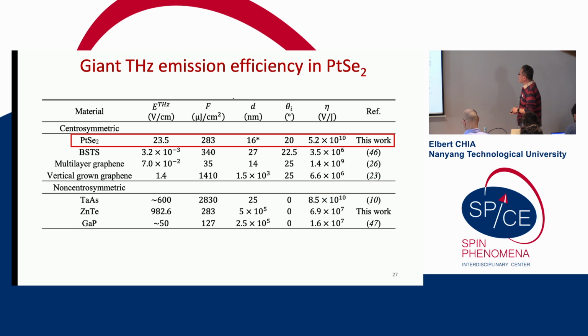We then went on to calculate the terahertz emission efficiency normalized to sample thickness. And we found that the efficiency eta is of the order of 10 to the 10, which is much larger than other centrosymmetric materials, and is comparable to the non-centrosymmetric tantalum arsenide. And so it's quite interesting that a centrosymmetric material, via the photon drag effect, can give such a large second-order nonlinearity compared to non-centrosymmetric materials, which supposedly should give much higher second-order effect.